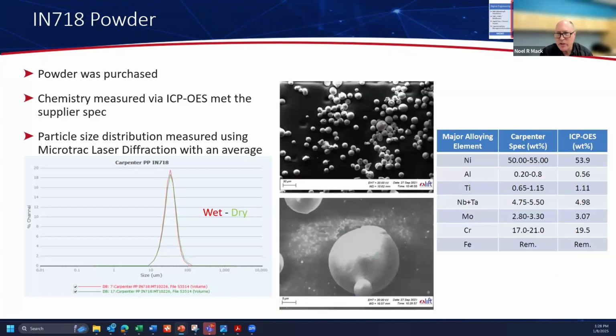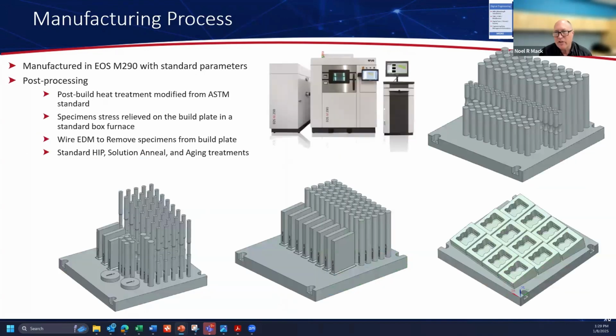So in this case, we actually purchased powder for this project because our capability was not yet commissioned. And first off, we evaluated the chemistry and the particle shape and size to ensure we had correlation with our simulation. We manufactured the test coupons with our EOS M290. So here's pictures at the bottom of the actual build plates as they've been built. You can see in this case, the geometries were not that exciting, being test coupons and wedges. We've done the post-build heat treatment with a modified ASTM standard, stress relieved the parts, and then removed them from the build plate using our wire EDM.